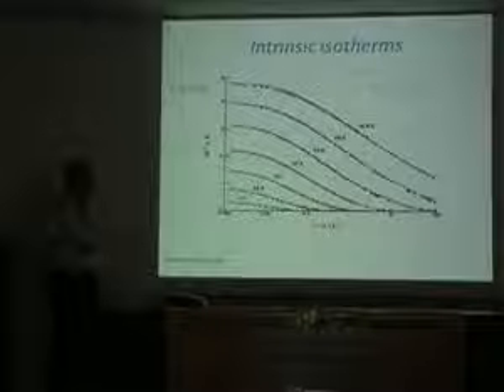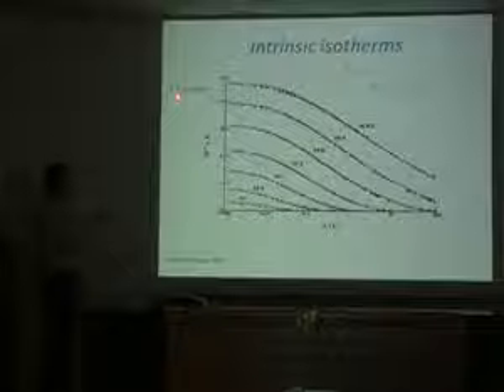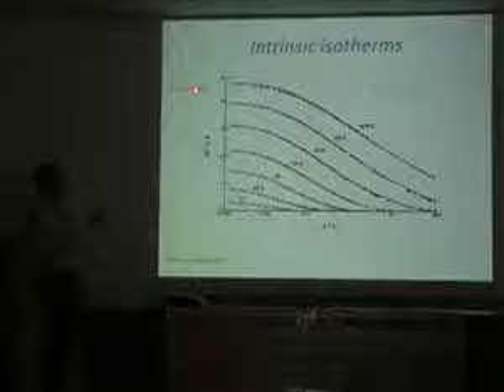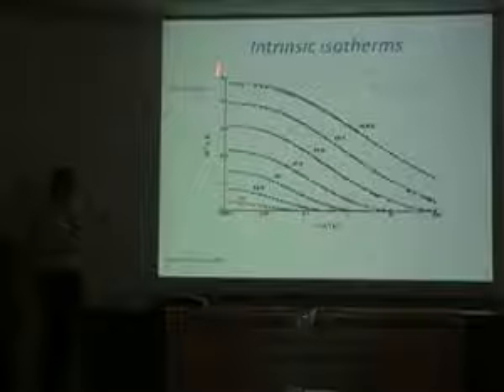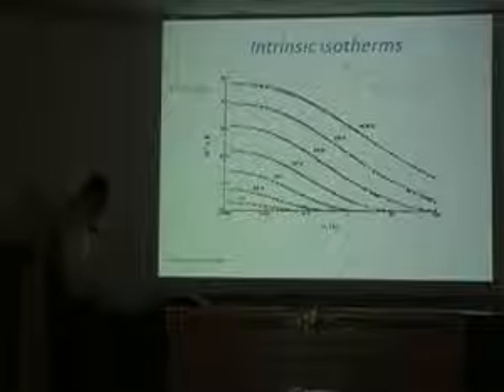And this is what Kovacs found. He defined a parameter, delta, equal to the current volume minus the volume at infinite time, divided by the volume at infinite time. So if I go back here, that's essentially the distance from here to here, but normalized by the equilibrium volume. Yeah? I'm just curious, if you follow the structural recovery, can you estimate the additional heat capacity that the system has, and do people make these measurements? People will also make heat capacity measurements, and I'll show results for those as well. People call that enthalpy recovery, and volume recovery is what Kovacs did, but in fact, they're virtually identical.